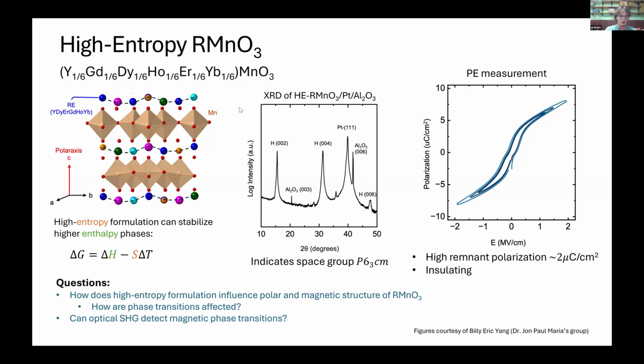So my job with SHG is to go in and confirm that the SHG still reflects the 6mm point group, that this matches up with the X-ray diffraction, because you could also get an orthorhombic phase, and then cool down and look for phase transitions, particularly magnetic ones.